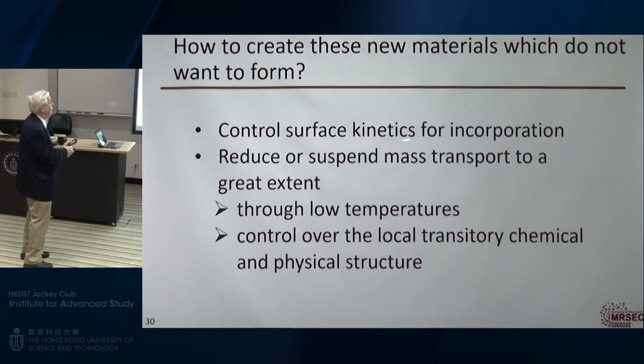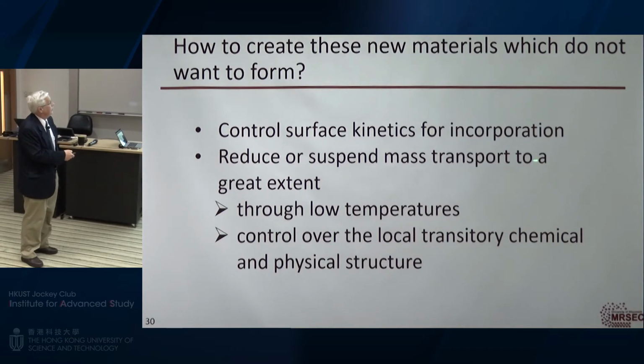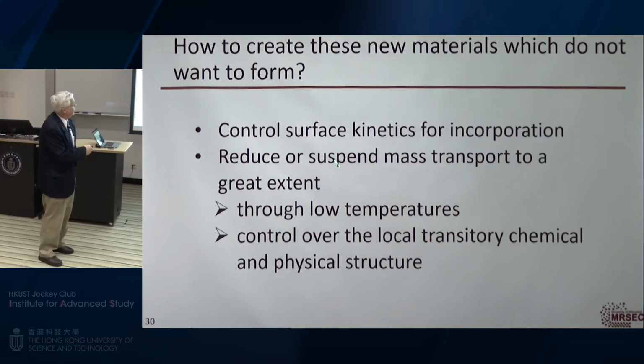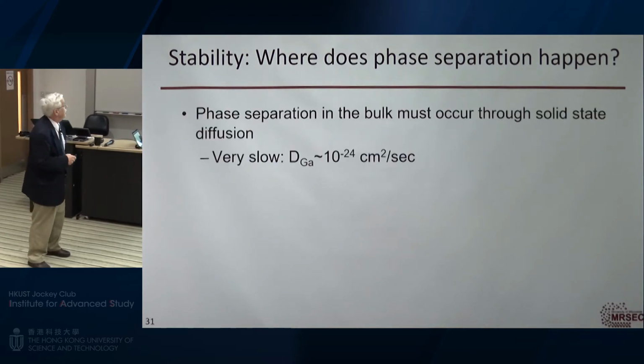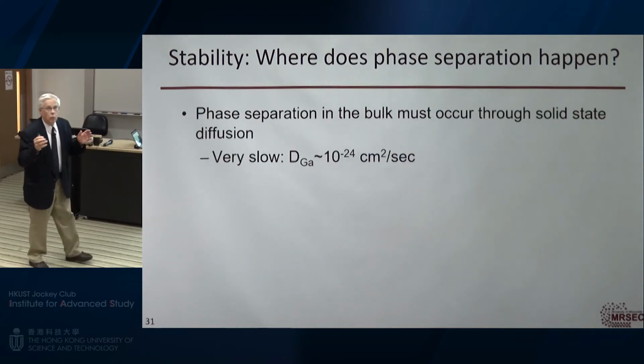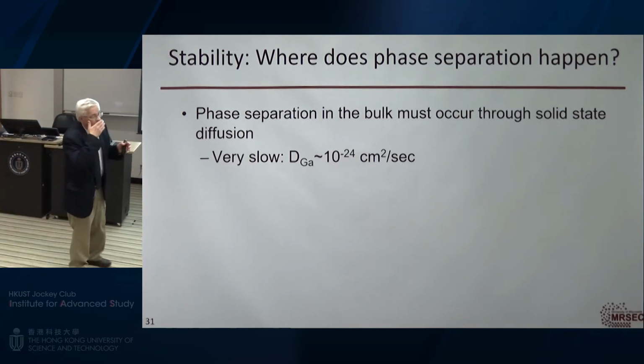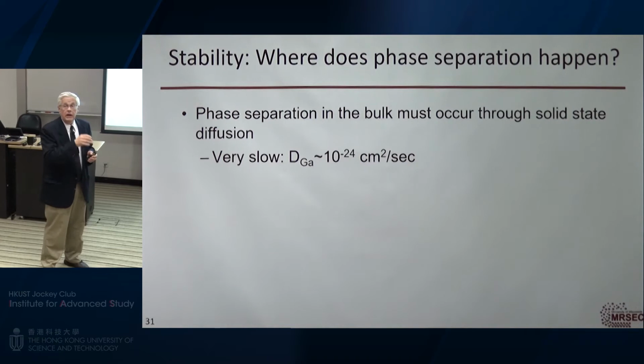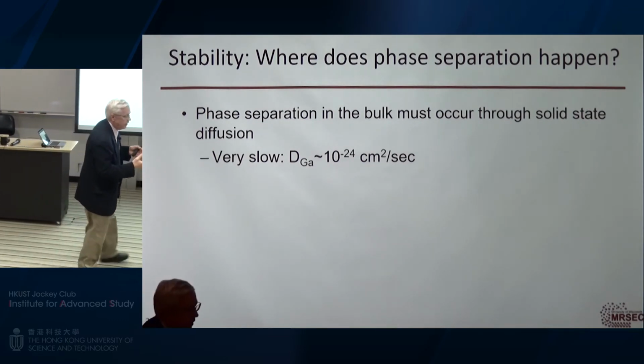Well, we're going to control the surface kinetics for incorporation of atoms. And that means reducing or suspending mass transport to a great extent. And we do this through low temperatures and control of the chemical and physical structure. So what does this mean? It means that if I want to keep things from phase separating, I have to say, where is that going to happen? If I actually made the material, so let's say I wanted to make some compound that was in that phase diagram, semiconductor, and it is thermodynamically unstable. Let's say I could make it, all right? Let's say I made it and it was the right crystal structure and right composition.